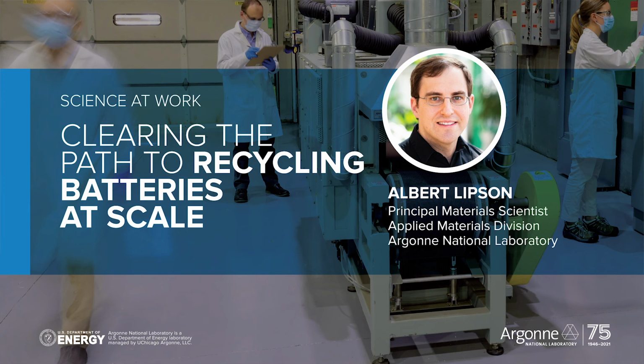And so what we figured out was we tested a whole range of different shredders, and we've determined basically which shredder produces the least amount of fines and therefore the least amount of contamination. And that's what we're using to move forward with this recycling process.